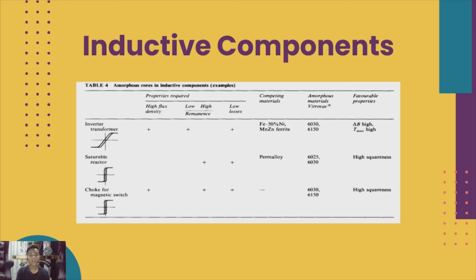Saturable reactor cores are another example where the hysteresis loop must be very square. They are used in a variety of applications, most notably as magnetic amplifier cores to regulate the output voltage of SMPS. To obtain a high efficiency, the remagnetizing drive current should be small. This requires a low coercivity. Apart from high hysteresis squareness, low dynamic losses of the core are clearly important in this application, which can be best addressed by thin ribbons of amorphous metal.